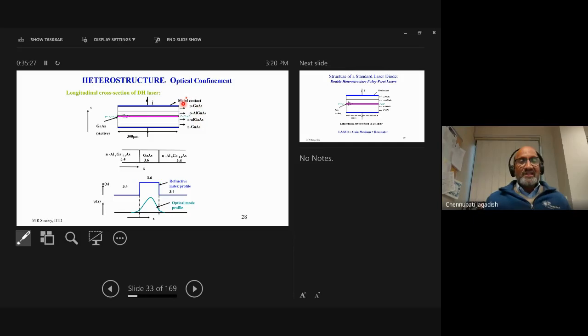Again, this gives you the details of the longitudinal cross section of this particular device: p-type gallium arsenide, p-type aluminum gallium arsenide, n-type aluminum gallium arsenide, and n-type gallium arsenide, with the light propagating here. Because gallium arsenide has a smaller band gap, it also has a larger refractive index, and that's how the optical confinement is created here. The optical mode profile looks like that because of these differences in refractive index between gallium arsenide and aluminum gallium arsenide. That allows you to keep the light in a particular area, create the waveguide, and allow the light to bounce back and forth.